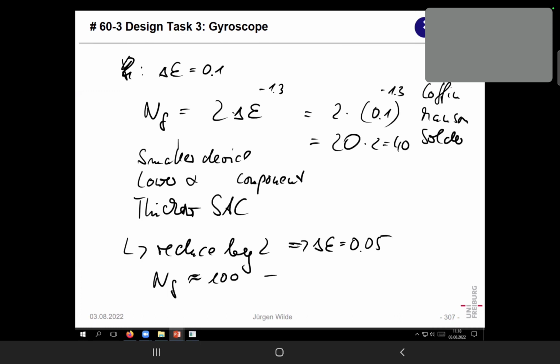Again, I would recommend that you recalculate the strain so that it is really 0.05 as an absolute value. Also, what is a little different in the QFN than, for instance, when you would have taken a BGA is that the height of the solder joint is significantly lower. In a BGA with, let's say, a ball diameter of 0.5 millimeter, it has a height of roughly 0.5 millimeter, or if it's 0.3 as a ball size, the height will be roughly 0.3, and that's significantly more. In that way, it was a combination which, as a product of several factors, led to such a high value.